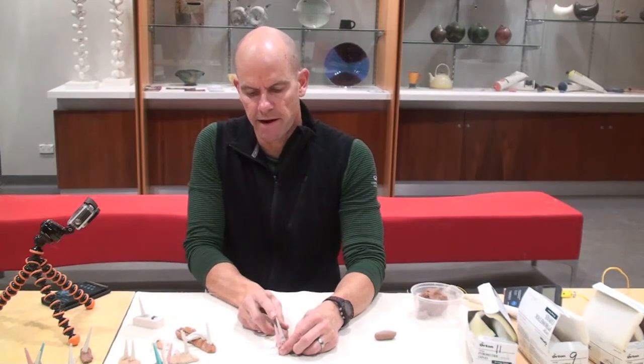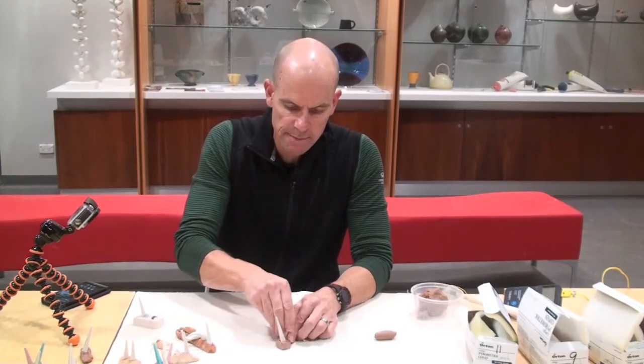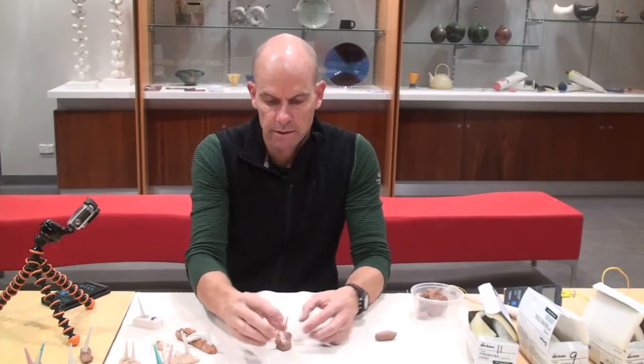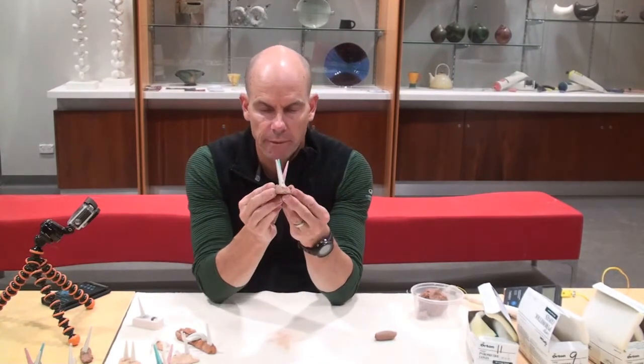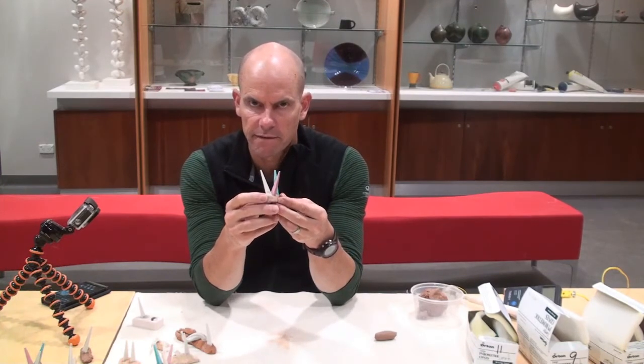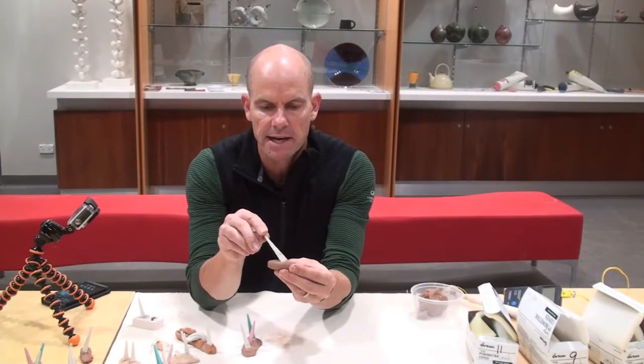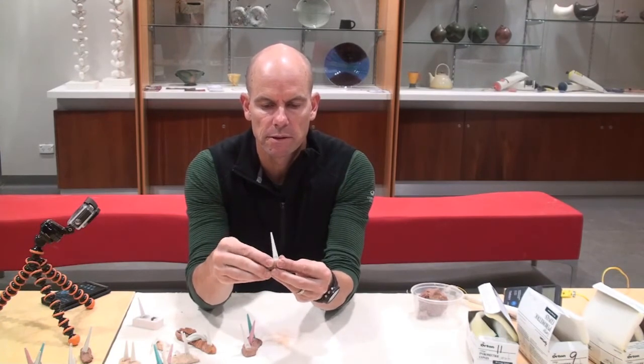Let's check the angle — I've bent mine a bit too far over. There we go. Now I'm going to do a cone 10, the temperature I'm actually aiming for, and then a cone 11. Notice I'm going back and forth, one side to the other. If you're looking into the kiln through the spy hole, you see one bend right, one bend left. I actually like that process — it helps to figure out what's happening. Make sure the cone is sitting far enough into the wadding, up to the bottom of the circle. If you don't do that, when the cone starts to bend it will fall out of the wadding all by itself.